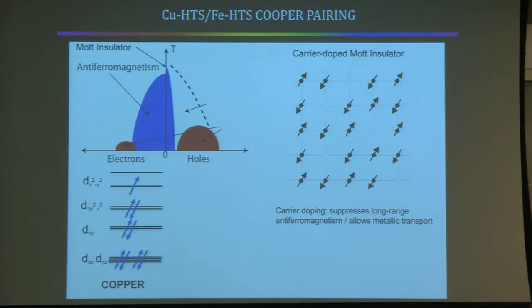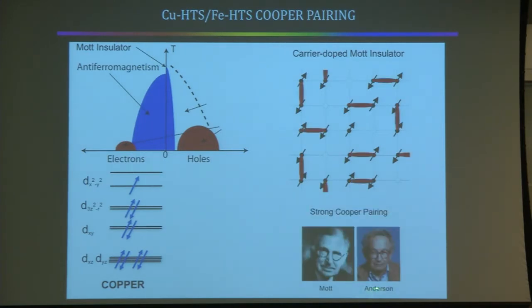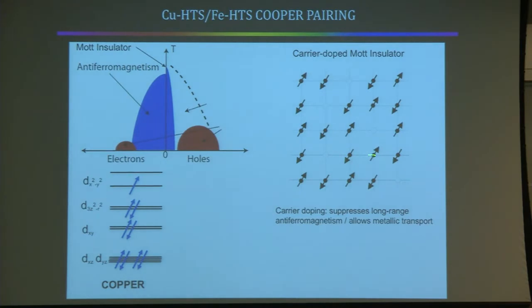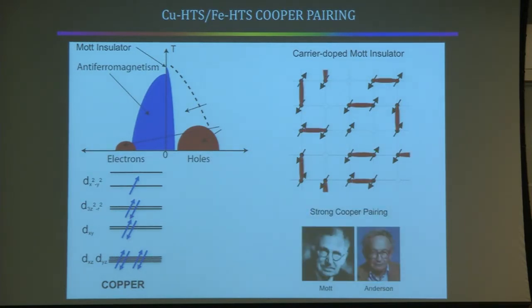So where could the superconductivity come from? Phil Anderson's proposal is that it comes from here. This magnetic interaction, even if you destroy the long-range magnetic order, the strength of the superexchange remains. If you want to minimize the free energy of the system, you could pair these guys into singlets and make a soup of singlets, which would be, according to the Anderson view, a high-temperature superconductor. So that would be lovely. If that was a universal solution, we should search for other Mott insulators which have high J, dope them, and then they should turn into high-temperature superconductors.